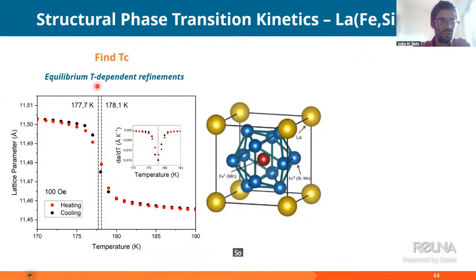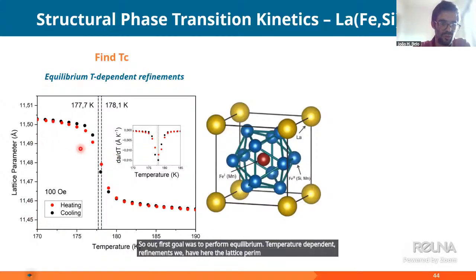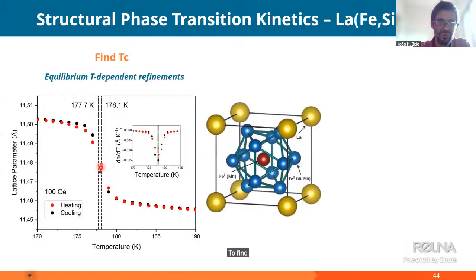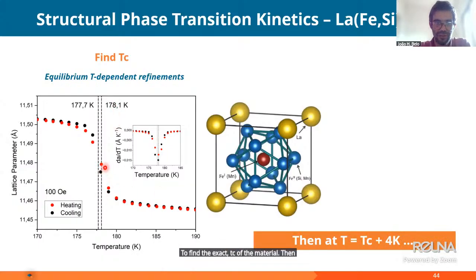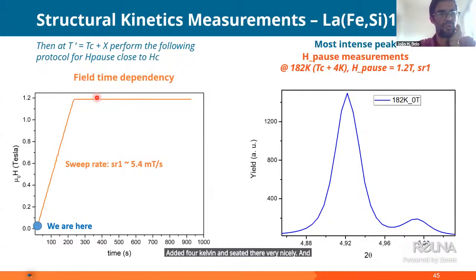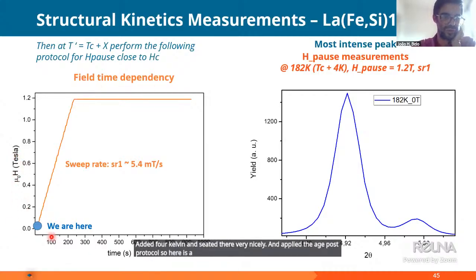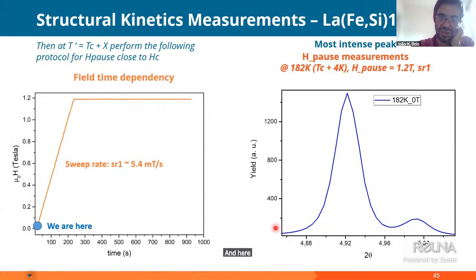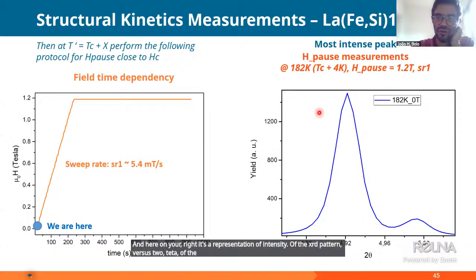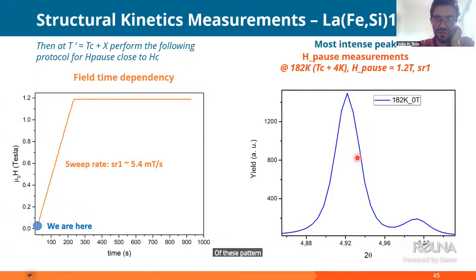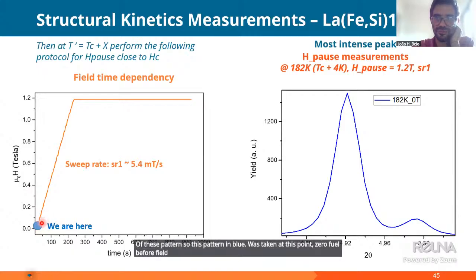Our first goal was to perform equilibrium temperature-dependent refinements. We have here the lattice parameter as a function of temperature for heating and cooling curves to find the exact TC of the material. Then we picked this TC, added 4 Kelvin, and sat there very nicely, and applied the H-pause protocol. Here is a representation of field versus time, and here on your right is a representation of the intensity of the XRD pattern versus 2 theta, focusing on the most intense peak of this pattern. This pattern in blue was taken at this point, 0 field, before the field started changing.